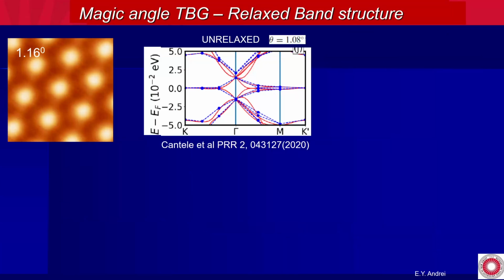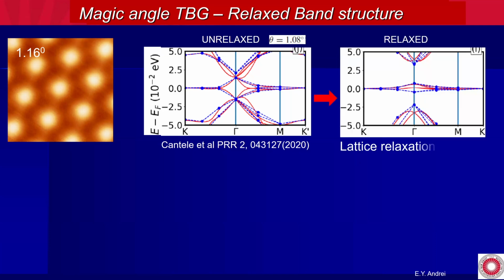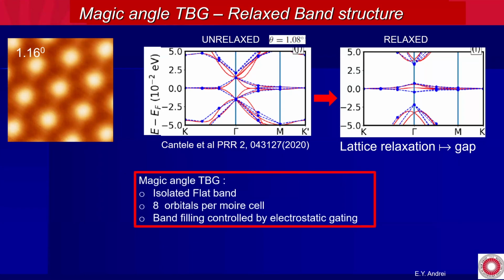Okay, so if you calculate the band structure without taking into account this relaxation, you see that there is a flat band, but it is continuously connected to the remote band. So such a flat band is not very useful for getting correlated states. You really want it to be separated from the remote band. So in fact, what the relaxation does is it opens up a nice gap to the remote bands, and then a lot of interesting things can happen if you are able to bring the Fermi level within that flat band. So here, we have an isolated flat band.